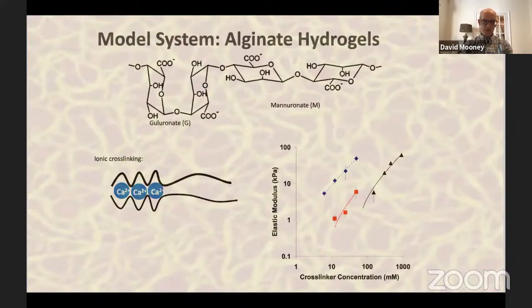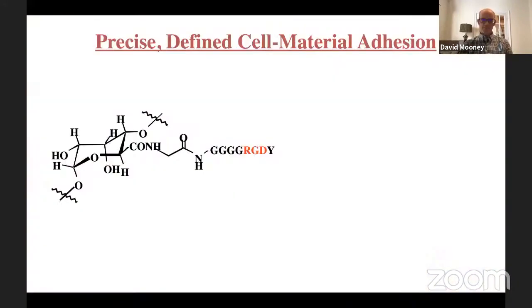And actually, the background image that you're seeing here is an AFM image of one of these alginate hydrogels. So you can see the individual polymer strands. They kind of look like pieces of spaghetti. And then you have the spaces in between, which are in the nanoscale. The mesh size in these gels is about 3 to 5 nanometers in size. And so the cells are immobilized and encapsulated within this gel.